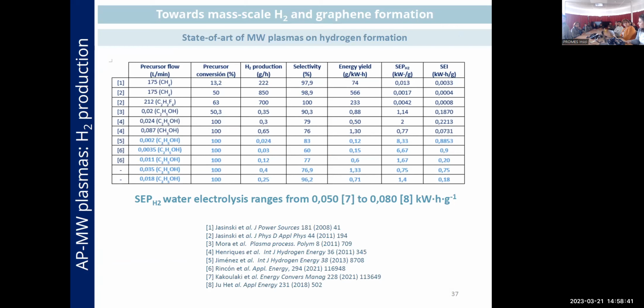Let's put these results in perspective. Here we can see a summary of the production of hydrogen by different microwave plasmas using different precursors and so on. In blue is the result that we have found in our research, and something that is really important from our equipment, from our discharge, is that we have almost 100% conversion of ethanol. Also, the selectivity of the process for hydrogen production seems to be high according to some experimental conditions, and we are minimizing the amount of energy that is needed for the formation of hydrogen.